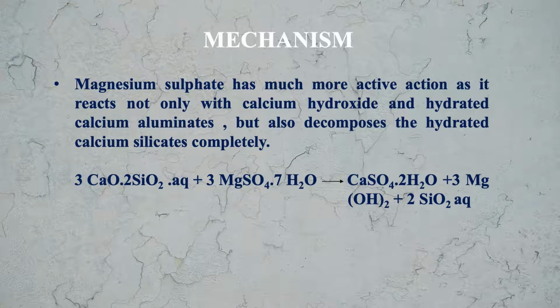Magnesium sulfate has much more active action, as it reacts not only with calcium hydroxide and hydrated calcium aluminates, but also it decomposes the hydrated calcium silicates completely. As you can see from this equation, tricalcium silicates, here it is reacting with magnesium sulfate and finally it is completely decomposing these hydrated calcium silicates.